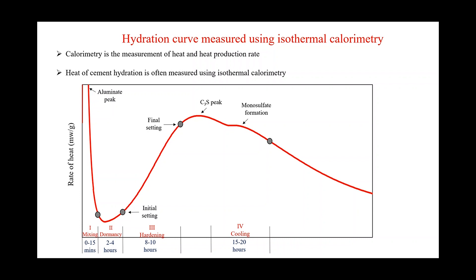After the C3S peak, the next stage is called the cooling stage. The rate of C3S reaction slows down and the heat generated begins to drop. The reason is that the buildup of C-S-H and C-H starts interfering with the contact between remaining water and unreacted cement grains. During this period, concrete is actually gaining strength — even though heat reduces, C-S-H and C-H formation continues.